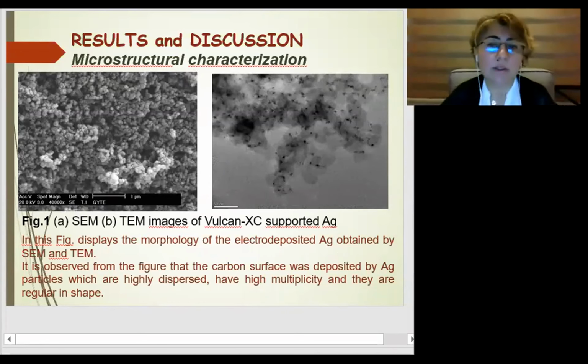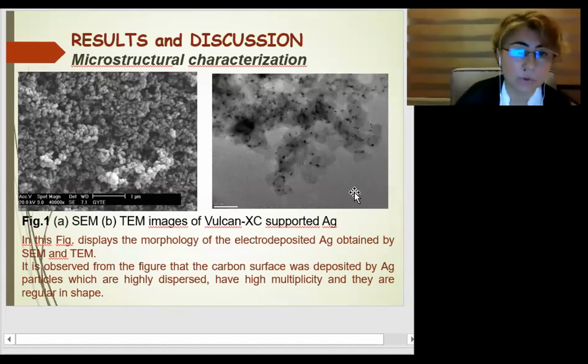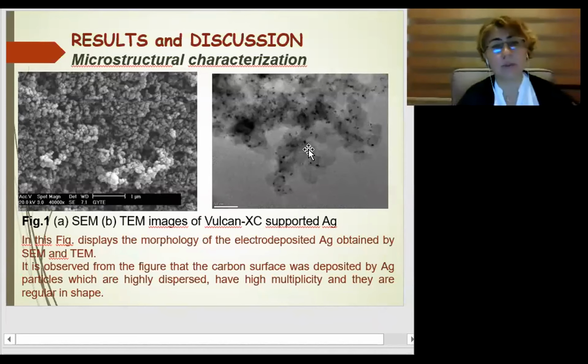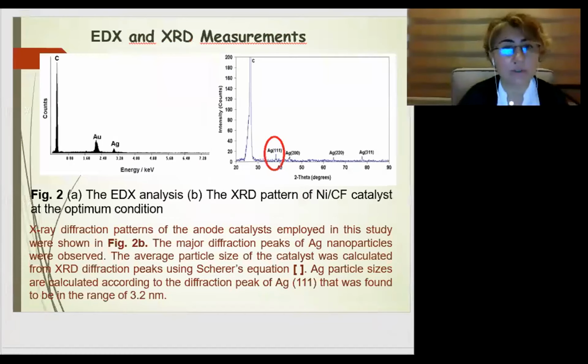The micrographs presented in figure 1 A and B display the morphology of the electrodeposited silver obtained by SEM and TEM. It is observed from the figures that the carbon surface was deposited by silver particles, which are highly dispersed, have high multiplicity, and are regular in shape. And you see the black points here in the TEM image. It's very clear.